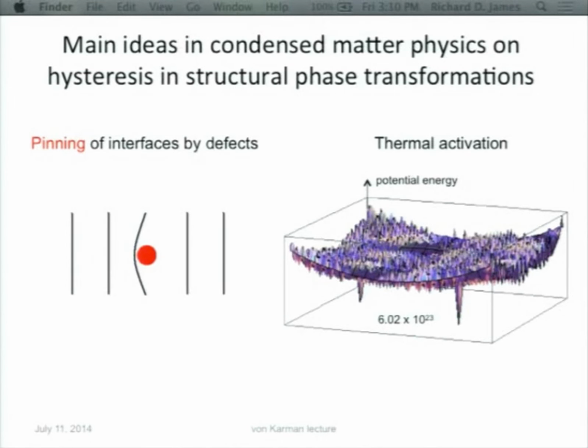Now, the state of the system could be given by a dot on this surface, and the dot would be moving around this surface. In fact, the equations of motion of the dot are the equations of molecular dynamics. So the belief is that as you raise the temperature, the kinetic energy of the system increases, and at some point it jumps out of this well and is delocalized on this surface, as indicated here. That corresponds to the phase transformation to the austenite phase. In fact, it may not even be at a local minimum of the potential energy.